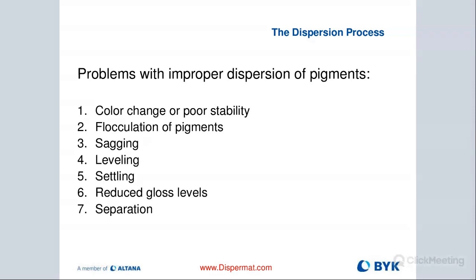So some of the issues that come up, if we do a poor job dispersing our pigments or particles, we're going to have very poor stability. We're going to have maybe a shift in our color. That comes up a lot. Flocculation of pigments, where they just bind back together and then they settle out, so they don't have any shelf life. Sagging, leveling, settling is another issue there. Reduced gloss levels or separation could be another issue if we poorly disperse. But I want to also stress